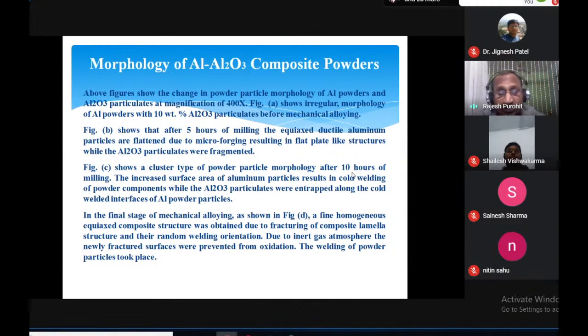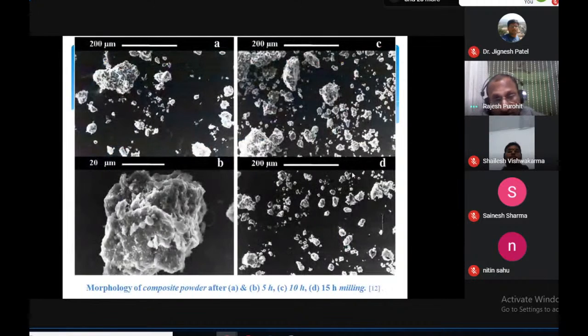The next figure, figure C, shows the cluster type of powder particle morphology. Clusters are formed from the particles after 10 hours of milling. The increased surface area of the aluminum particles results in cold welding of the powder components, while the aluminum oxide particulates are entrapped along the cold welded interface of the aluminum particles. I'll show it again. These are the flattened aluminum particles, and aluminum oxide particles get mixed with them, and here they are getting mixed again.